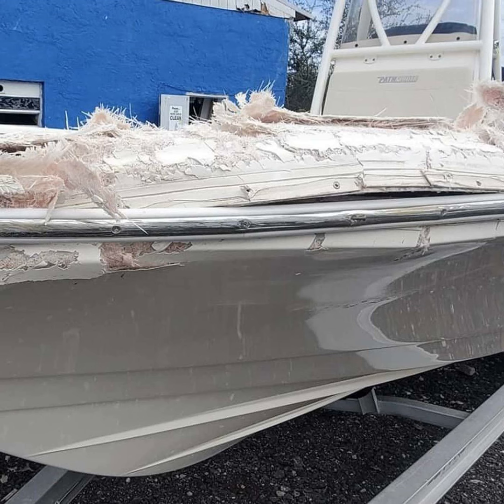You can also notice some stress cracks inside strakes sometimes, and a lot of times those strakes are directly underneath the stringer. Most manufacturers try to run their stringers where at least one side of the stringer lands on a strake, if they can, or over it sometimes. So if you look underneath a boat, maybe you're going to buy it or you're just doing an inspection, you want to look in the armpits of those strakes, for lack of a better term. I'm not sure what the proper term for that is, but look inside the corner that the strake makes running down the boat. If you see a crack that runs the entire length of the boat, especially on both sides, that's definitely indicative that you have some structural damage.